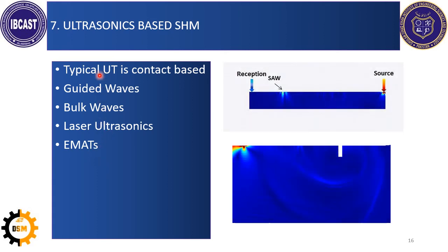Another orientation of ultrasonics is the EMATs. These are electromagnetic acoustic transducers. They are a modified form of eddy current. Based on the Lorentz force produced, they produce ultrasonics in conductive surfaces. These are good in a way that they are non-contact and they don't need glycerine or other couplant, as is needed with typical piezoelectric sensors. So we are working on these to detect railroad cracks, and in future I will use them for CFRP laminates as well.